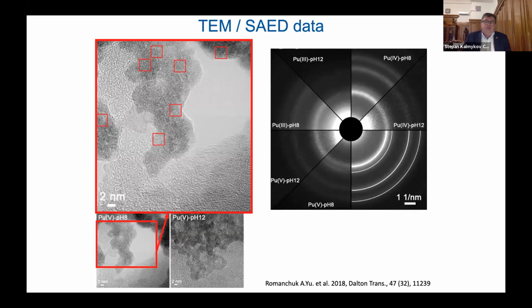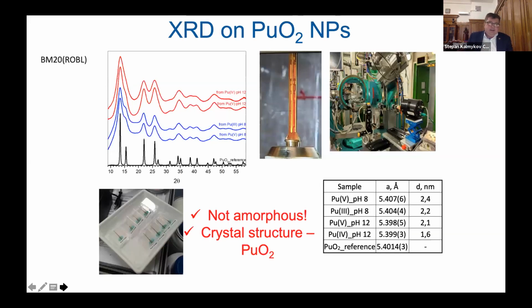But we always have to remember that when we use TEM or any very local method, certainly we can drop down to visualize separate atoms, as you can see in this image. But you always have to remember, you have a large sample that contains, for example, millions of different particles, and we can visualize only, let's say, tens, hundreds, maybe a little bit more particles. So this means that TEM is not representative for the characterization of the whole sample. That's why TEM and any local measurements should be supported by spectroscopic methods that can characterize the whole sample.